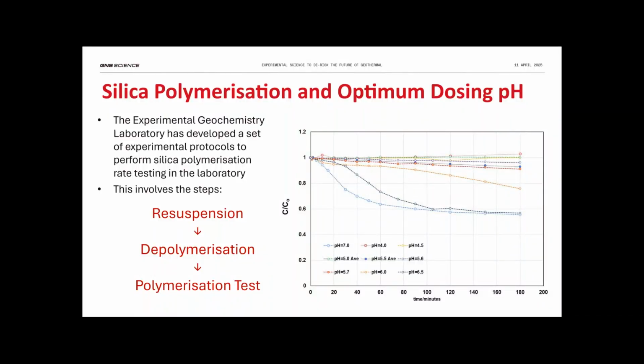And now we are able to do silica polymerization testing in the laboratory. Now the three steps involved are the resuspension, because typically when brines come from an area with a very high salinity, the silica is flocculated by the time we receive it. So we actually get a silica flock in the bottom of the sample containers. So first step in there is resuspending the sample, and we have ways of doing that.